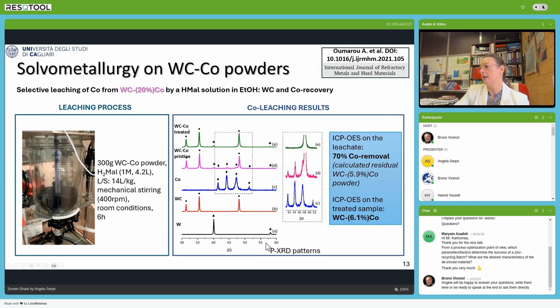In this graph on the right, you can see the XRD pattern of the material before the treatment. So the pink pattern is related to the pristine material, where the two phases, the tungsten carbide and cobalt phases, are visible, and instead the green graph reports the material after 6-hour leaching, where the cobalt is difficult to see in the pattern.